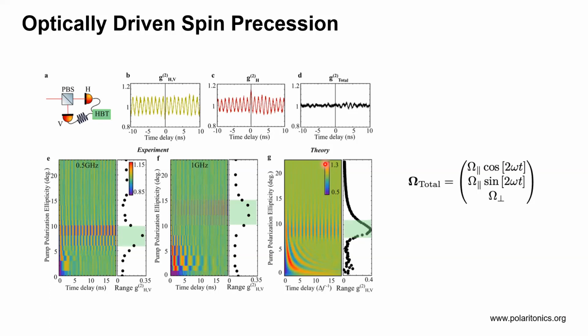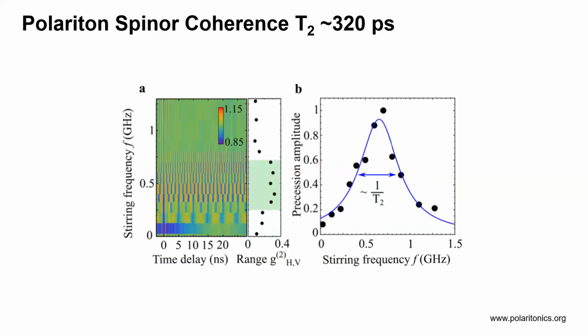So I can now have optically driven spin precession inside this polariton trap, and I can do the classic experiment of measuring the spin coherence, and we see that we reach spin coherence of 320 picoseconds for a system that interacts within a couple of picoseconds. So I have room for a lot of operations there. And then with that, I will close. That was, I know, a bit too much.